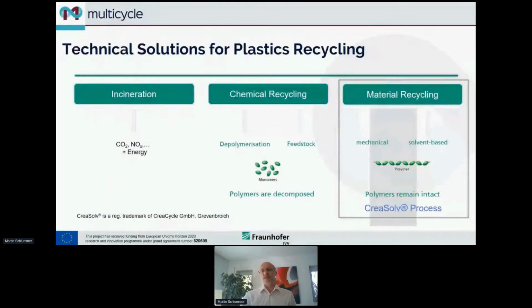In contrast to that, we have material recycling. And here we have the classical mechanical ones. We all know where you take the in-feed, you have a shredder, you have some cleaning ideas, mainly mechanically, some washing, some sifting, metal recovery, whatever. And in the end, there's something which is rather purified polymer and which is then re-extruded, melt filtered, and so on. This works quite fine, but not really well for fiber reinforced material with glass fiber contents up to 50%. Another idea could be the solvent-based technology, which I will present here today.